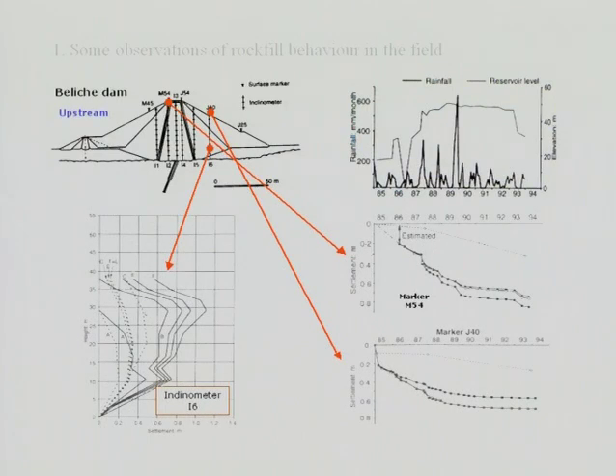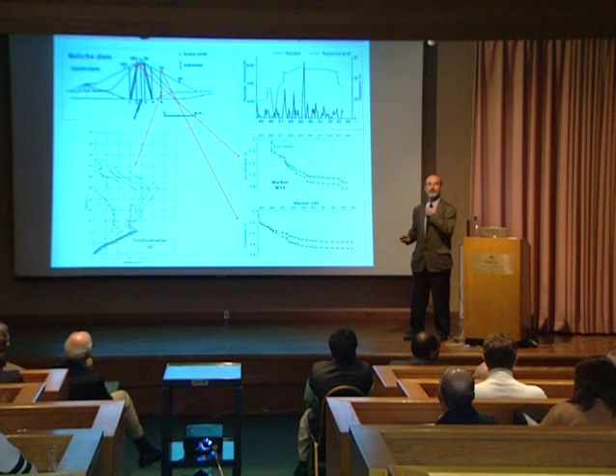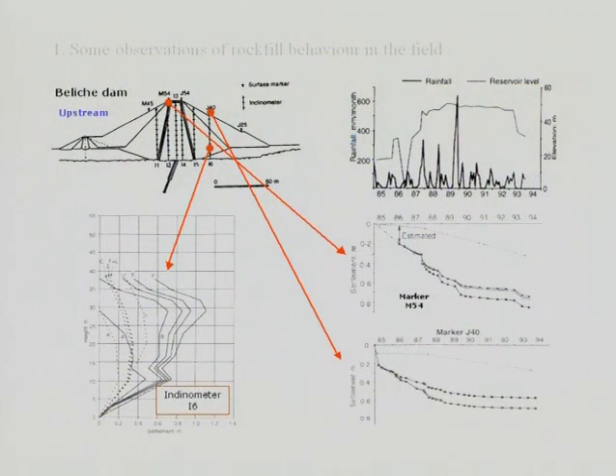And this dam has been analyzed in several papers. There have also been attempts to make Class A prediction for it. And here you have a number of marks for which we have data, and also for some inclinometers. And you have here on the right the history of the water level in the reservoir. There was an accidental partial filling in 86, and then the final filling in 87, 88. But you see also the record here of the rains, and you can see how those markers show settlements that can quite nicely be correlated with the intensity of the rainfall.